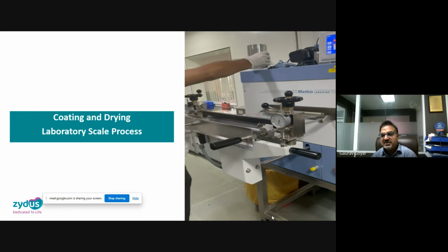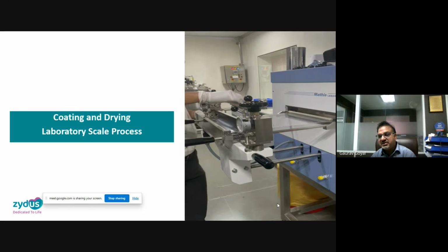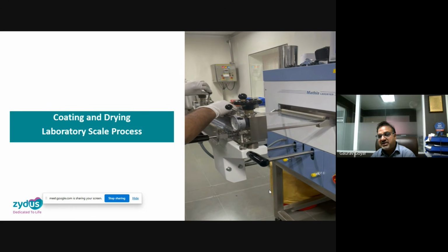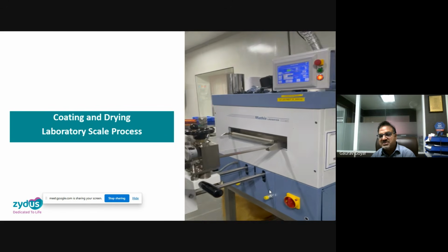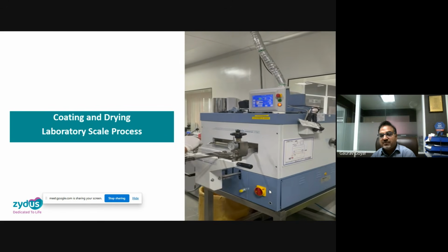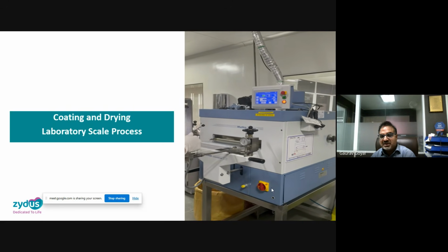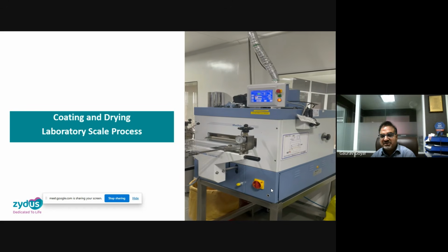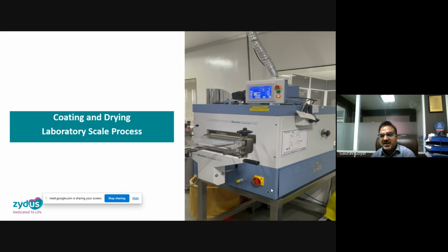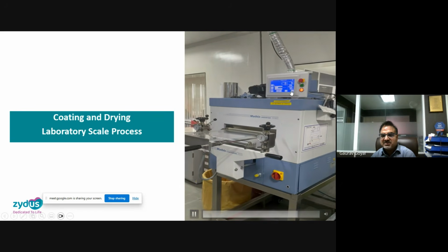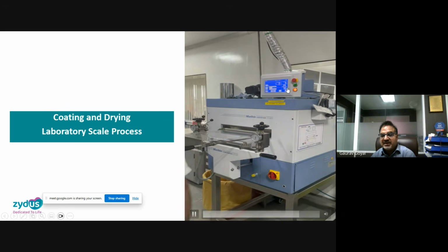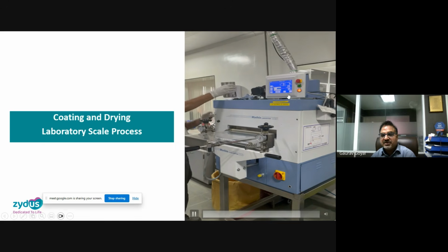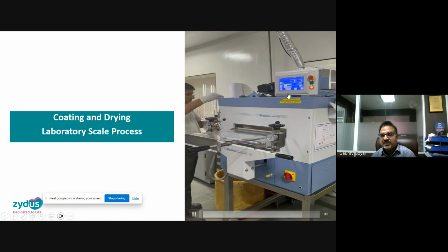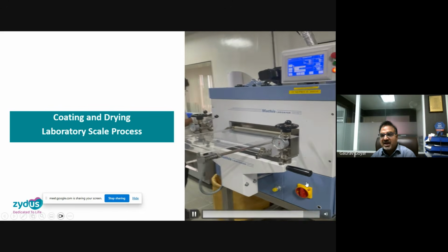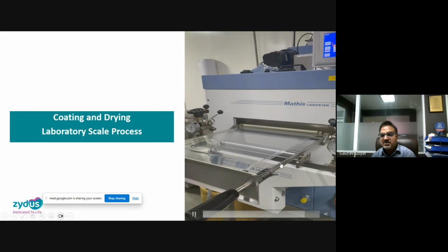The blade is coming and the wet coating is done, and then this wet, coated part goes inside the machine for drying purposes. This particular assembly will go inside the machine, and then after drying, there are set critical process parameters, the drying temperature and the drying blower speed, where it dries and the solvents get evaporated and the film becomes dried.